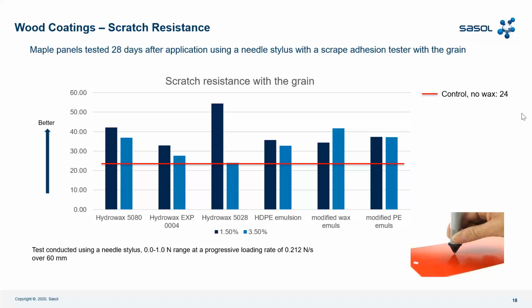So we can see that Hydrowax 5028 at 1.5% achieves the best results, and outperforms the other products and also the competition. Then follow Hydrowax 5080 and Hydrowax experimental 004. So in this test we show that for scratch resistance with the grain, Hydrowax 5028 at 1.5%, wax plus polymer, achieves the best results, promising. Then this was the scratch resistance with the grain.